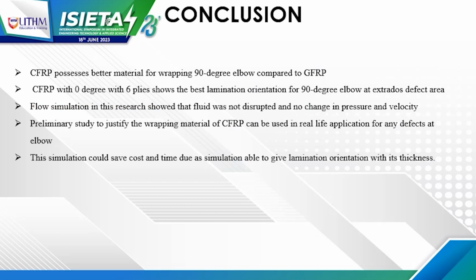For conclusion, CFRP is a better material for wrapping a 90-degree elbow compared to glass fiber. Carbon fiber with 0 degree and 6 plies shows the best lamination orientation for a 90 degree elbow at the extrados defect area. Flow simulation in this research showed that the fluid was not disrupted and there was no change in pressure and velocity. Preliminary studies justify that the CFRP wrapping method can be used in real-life applications for any defects at an elbow. This simulation could save cost and time, as simulation is able to give the lamination orientation with thickness. Thank you.